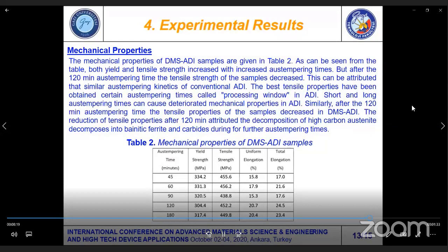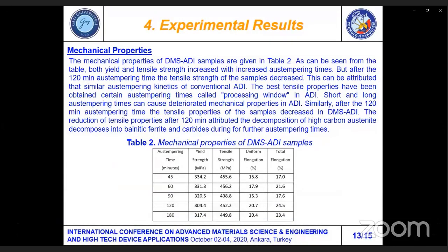Similarly, after the 120 minutes austempering time, the tensile properties of samples decreased in dual matrix structure austempered ductile iron. The reduction of tensile properties after 120 minutes is attributed to the decomposition of high carbon austenite into ferrite and carbides during the further austempering times.